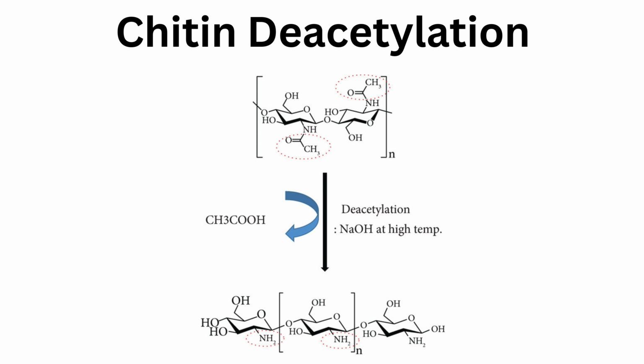Deacetylation of the chitin, which is also achieved during alkali treatment, is expected to release amino groups, which will facilitate additional cross-linking sites on the chitosan backbone structure in the mycelium. In addition, the deacetylation process has also been noted to improve the antibacterial properties of fungal chitin, making the deacetylated fungus-derived materials more suited for applications such as bioactive wound dressing materials.